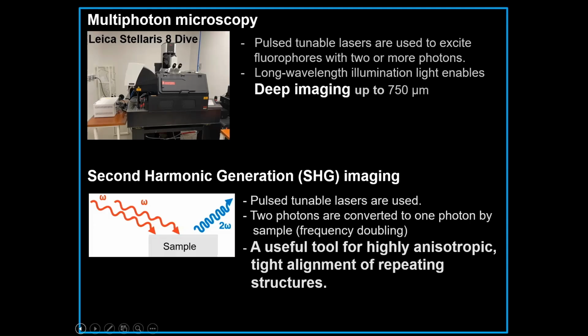And with pulsed laser, we can also do second harmonic generation imaging. We call it SHG. Pulsed tunable laser is used for that. What is happening is that 2 photons are converted to 1 photon by the sample, and the incoming wavelength frequency gets doubled after interacting with the sample. So if we are using, let's say, 900 nanometer incoming wavelengths to illuminate the sample, then after interacting with the sample, it gives 450 nanometer wavelengths.